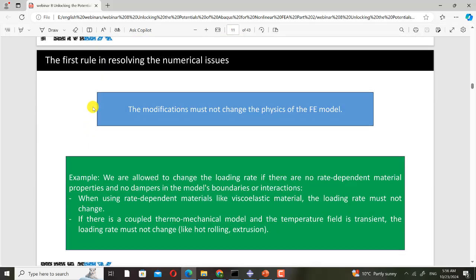Now I want to talk about the first rule in resolving the numerical issues. The first rule is the modifications must not change the physics of the FEA model. I explained it before. For example, we are allowed to change the loading rate if there are no rate-dependent material properties and no dampers in the model's boundaries or interactions. For example, when using rate-dependent materials like viscoelastic material, the loading rate must not change, because if you change the loading rate, then the material will change because it is rate-dependent. Or if there is a coupled thermomechanical model and the temperature field is transient, the loading rate must not change, like hot rolling or extrusion.